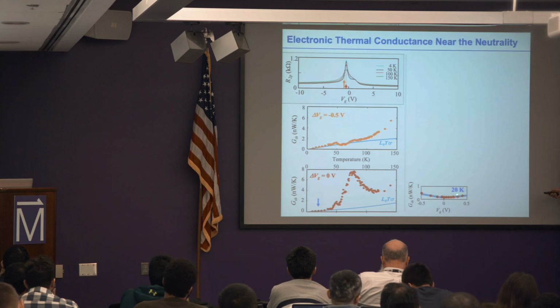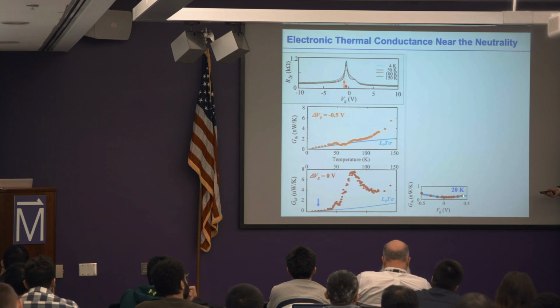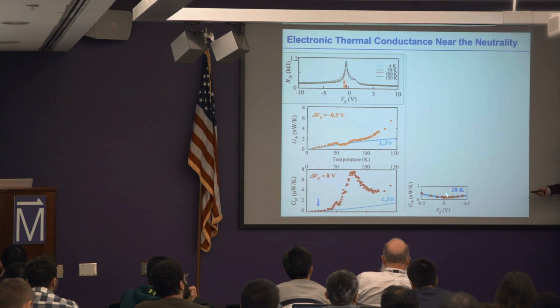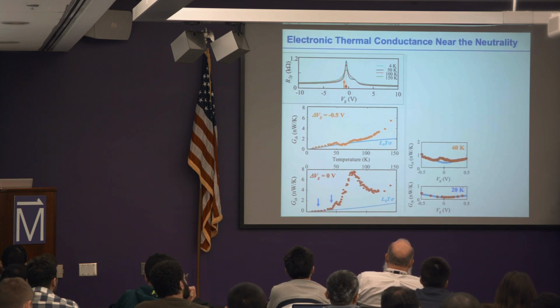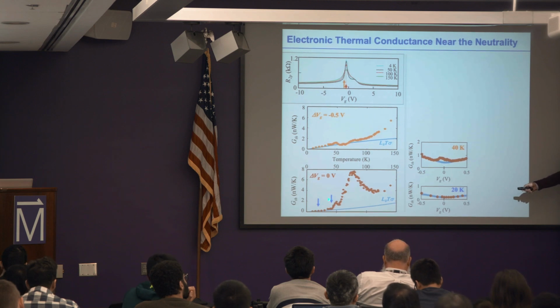So at 20 Kelvin, I'm showing you the sweep through the gate voltages. Away from the Dirac point, my thermal conductance and electrical conductance overlap each other, right? The Wiedemann-Franz law works at 20 Kelvin. At 40 Kelvin, right at the Dirac point, there are blips now, right? So there are some deviations, right? Now, that's where I start to see the deviation.